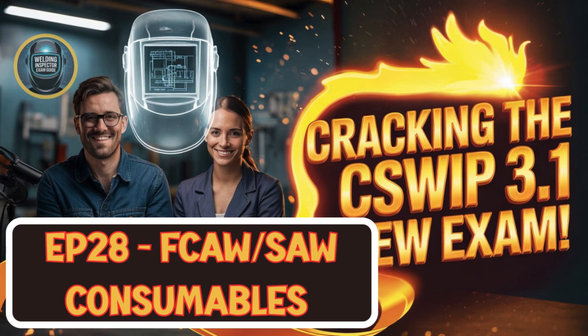Wow, okay. Hard stuff. And because of that high temperature process, it's actually impossible to incorporate certain heat-sensitive alloying compounds, like ferromanganese. They'd just be destroyed. Fused fluxes tend to be acidic in nature, and while they're quite tolerant of, say, poor surface conditions and generally easy to use, they produce a good weld contour, and the slag, the glassy layer left after welding, is usually easily detachable, but they typically yield comparatively lower quality weld metal, particularly in terms of tensile strength and toughness. Okay. So if they're harder, can't have certain alloys added and produce slightly lower quality welds, what's the upside? Why use them?